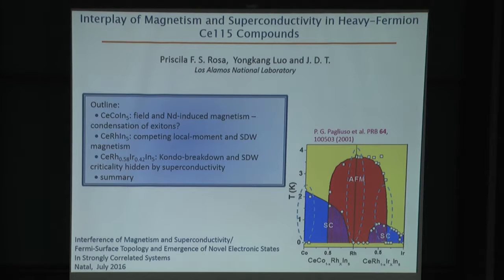And we'll show that there's evidence that both of these spin density waves may be due to the particular D-wave symmetry of the superconducting gap of cerium-cobalt-5. Well, cerium-rhodium-5 orders magnetically at atmospheric pressure, but applying pressure, you can suppress this magnetism and induce superconductivity. And in this case, we'll show that there can be competing cerium-derived magnetism and a spin density wave magnetism, where these two magnetic orders have very different origins, yet they both exist in the superconducting state of cerium-rhodium-5.